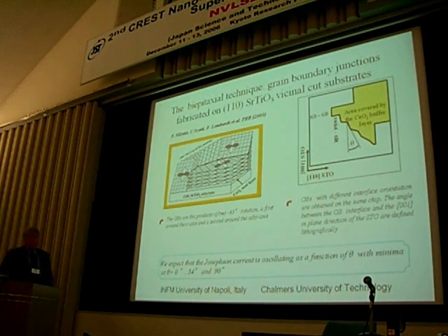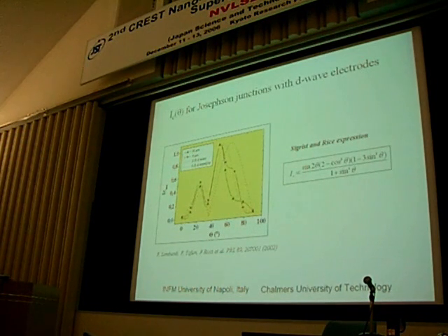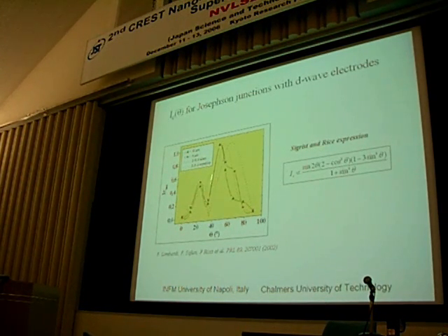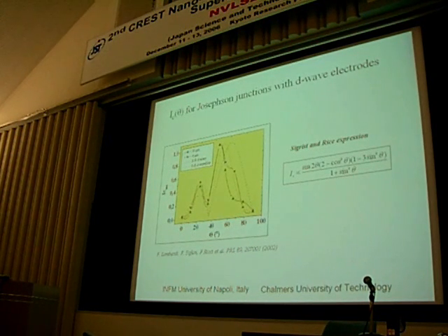What you find there is that the critical current — because it's a D-wave superconductor, I won't get into that, it would blow my time totally — but what you find here is that the critical current is very strongly dependent on the angle between the grains. And imagine that in the barrier region, or in one of the electrodes, we have a grain which is slightly differently oriented than the rest. That means in this area the critical current is already drastically changed.